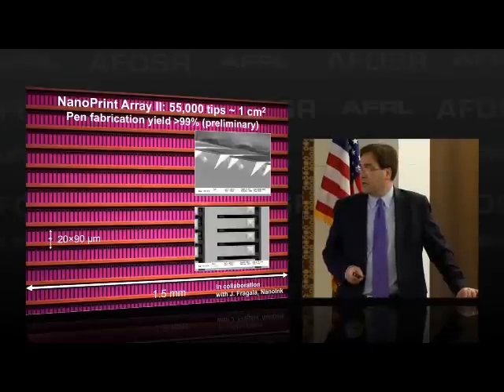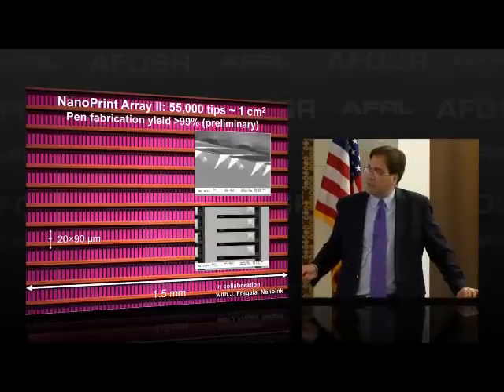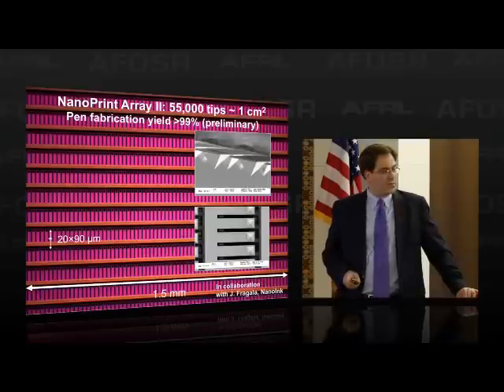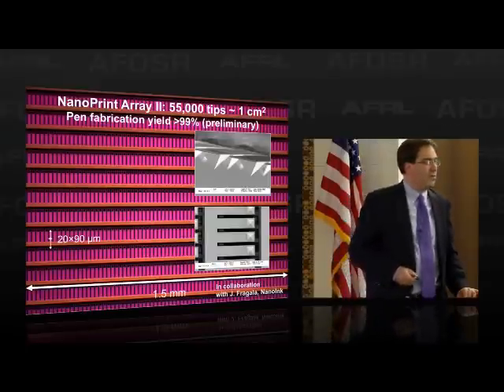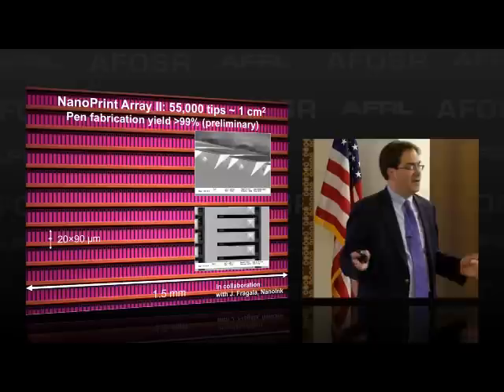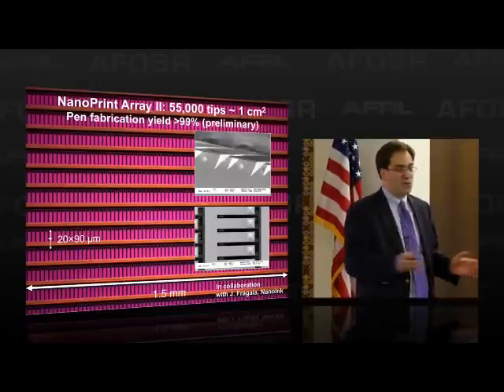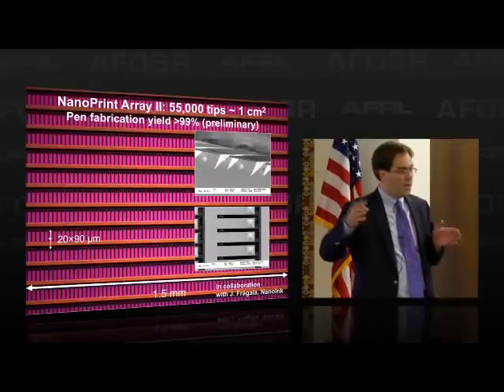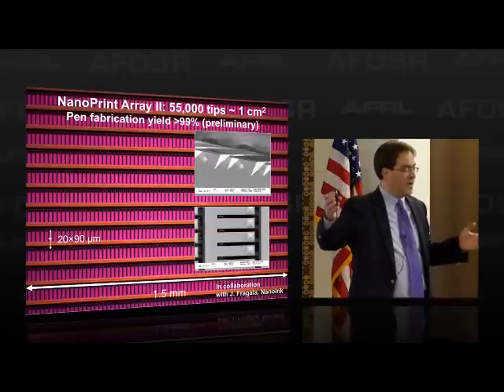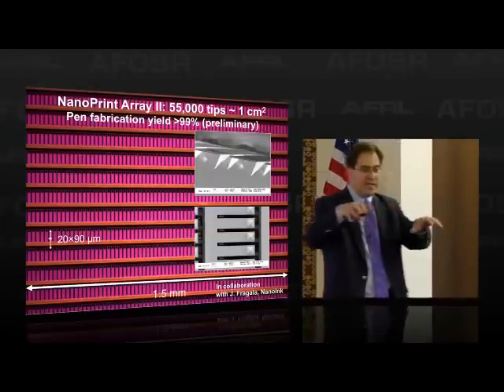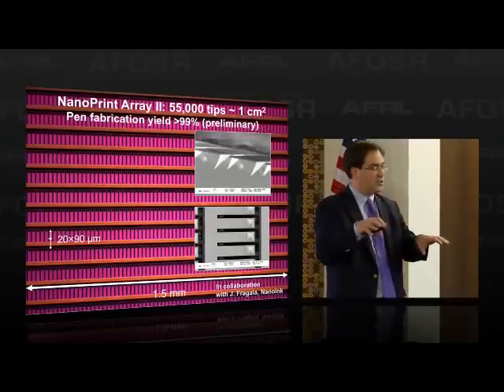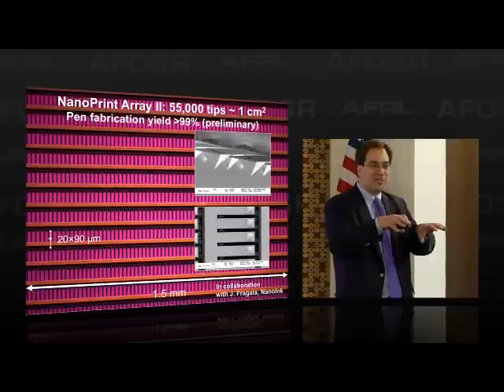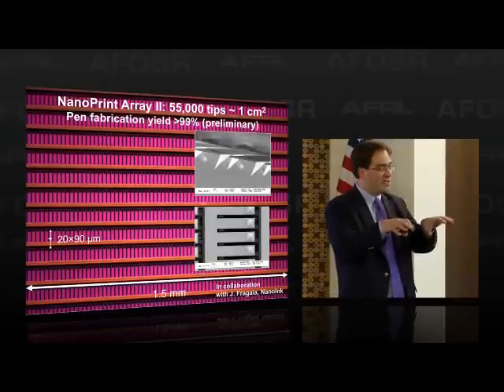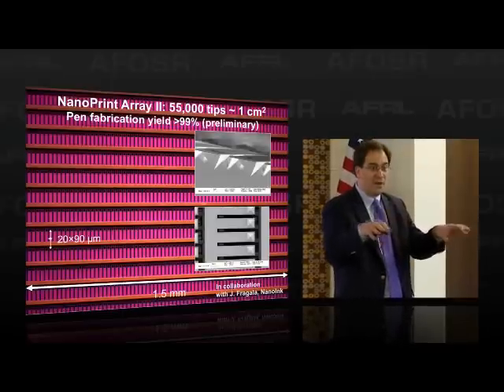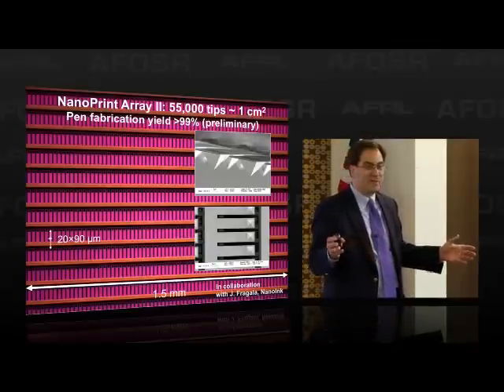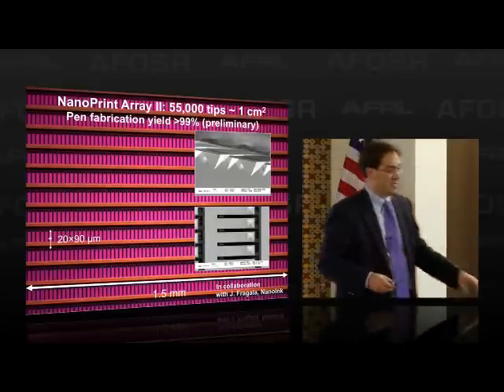Why is that important? Well, that turns out to be a critical observation, because a very talented postdoc in my group, a guy named Sung-Eun Hong, said, you know, what we can do with this is we can build large arrays in principle, and we can overcome one of the biggest problems in this complexity versus capability issue. Remember I said we want to go to big arrays ultimately, but we want to keep it simple. Well, the millipede approach to that, in terms of creating these little heated structures, is they put a little feedback system and heaters on each tip, and now they can regulate the positions of those tips, and how hot they are and how cool they are. The problem is that becomes a nightmare from a complexity standpoint.